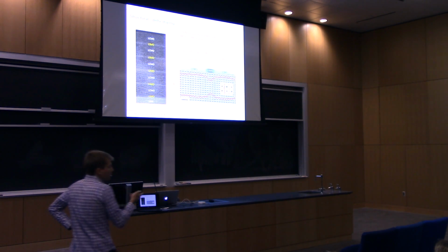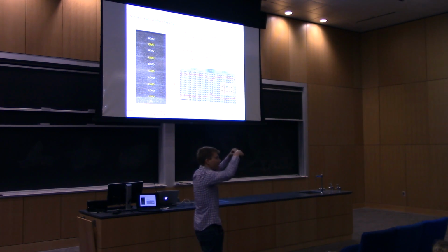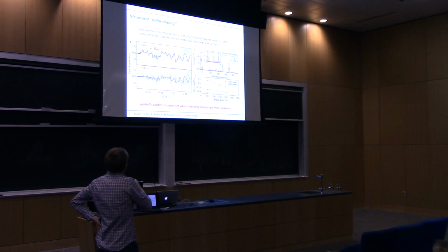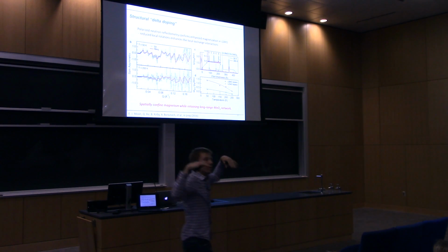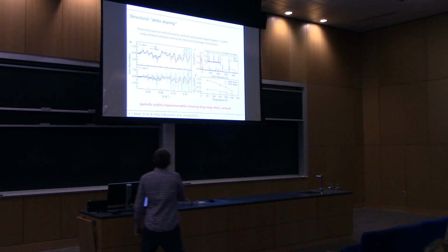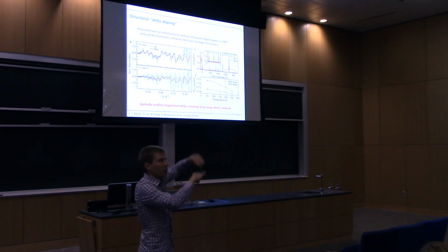All right, so these are, again, STEM images by the Oak Ridge folks. And here's the STEM image of the superlattice. Locally, they can use bright field imaging and look at the projection of the oxygen positions. And they see that locally within this LSMO, they get a reduction in the magnitude of these rotations, just like what we would expect. And again, we can then go to polarized neutron reflectivity, and here are the fits to the spin asymmetry. We can see that we get this enhanced magnetization inside the LSMO layers compared to the LCMO matrix. So this shows that we can use this structural delta doping technique to spatially confine magnetism within a coherent 3D crystal.